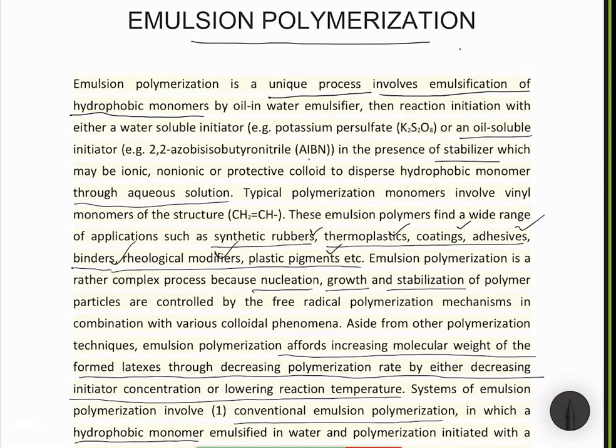the nature of the emulsion could be oil in water, that is your hydrophobic monomer dispersed in water, or any polar liquid, mostly water is used, so that way it is called oil in water emulsion, which is the general or the normal emulsion. And in that case the reaction is initiated with a water soluble initiator, that is, a water soluble initiator like potassium persulfate, so that way it is different from the suspension polymerization where we have used monomer soluble or oil soluble initiator.